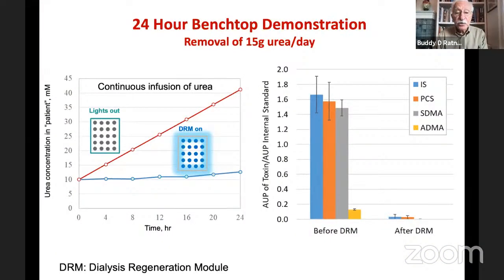How does it work? Well, here's some real data. On the left, you can see the experiment. What we're doing is continuously infusing urea into a tank at about the same rate your body makes urea a day. This would lead to about 15 grams of urea added into the tank during the day. And with the lights out on the DRM, the dialysis regeneration module, you can see the red curve, the urea concentration is steadily going up in the tank.